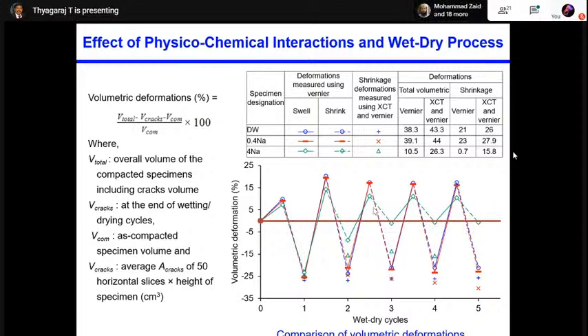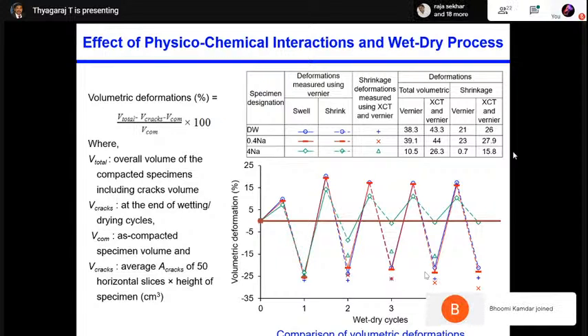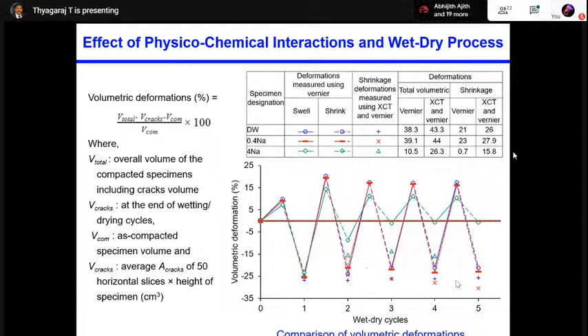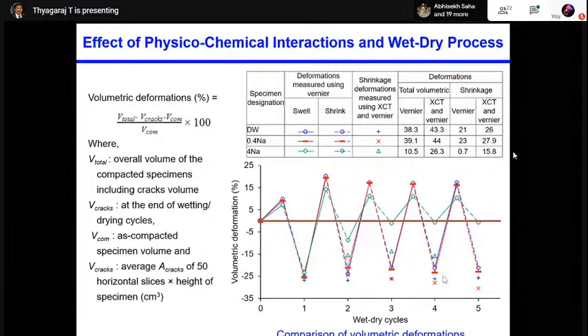However, the volumetric shrinkage of the 4 molar NaCl solution is far lower than that of the distilled water and 0.4 molar NaCl solution. From this figure, you can see that the 0.4 molar solution does not have much effect on the volumetric shrinkage. Further, we have used the XCT method, and we have also shown it here. One is digital, one is with the vernier calipers, just the vertical measurements. Using that and the area, we calculated the volumetric deformation. With the different fluids, the XCT measurements also clearly show the volumetric shrinkage. I will not go into that; it's just a basic one.